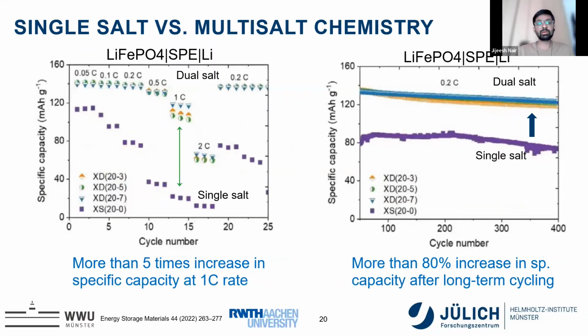And most importantly, when you cycle these kind of systems against lithium iron phosphate or other kind of cathodes, you will see that there is at least 5 times increase in the specific capacity at a higher C rate. Because C rate is important, because 1 C rate means that you charge for 1 hour and discharge for 1 hour. So when you have a car, you don't want to stay for 1 hour. Maybe you want to stay there for 10 minutes and you want to charge your battery. So this is where the C rate is important.